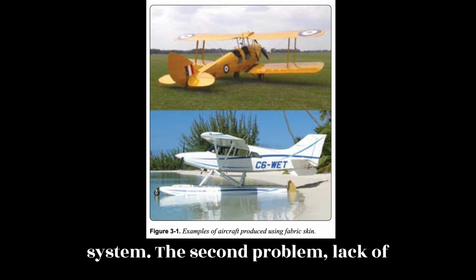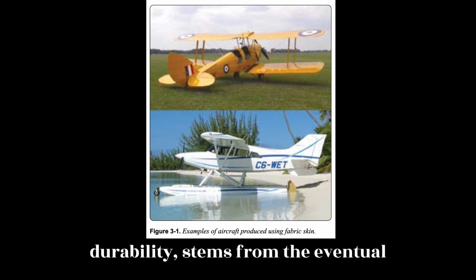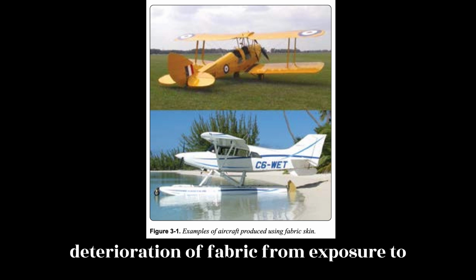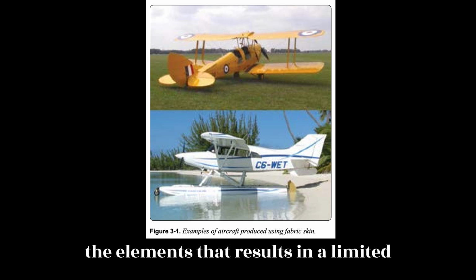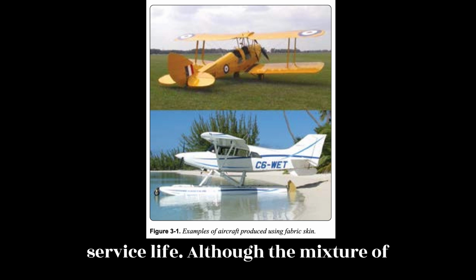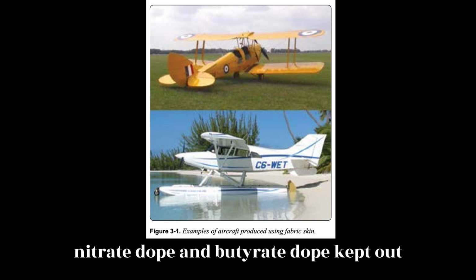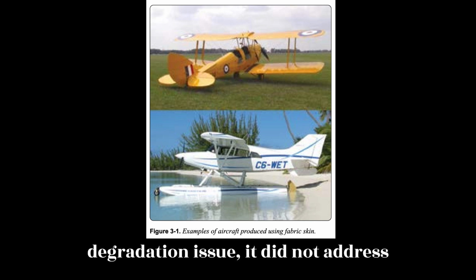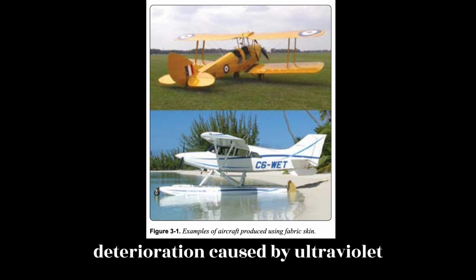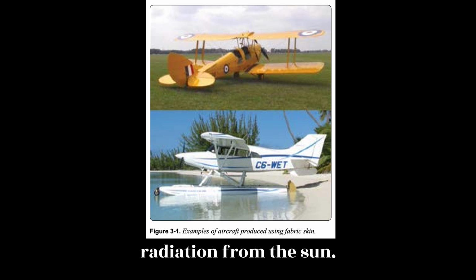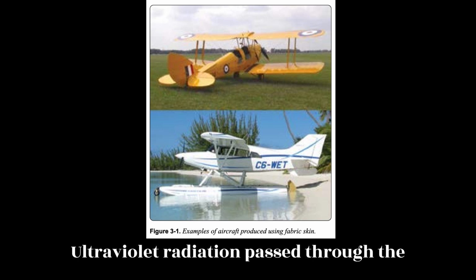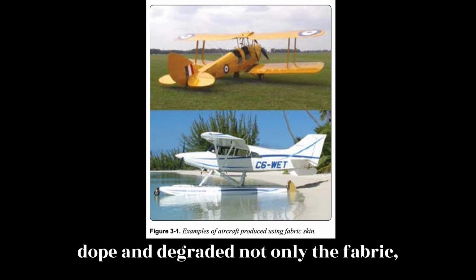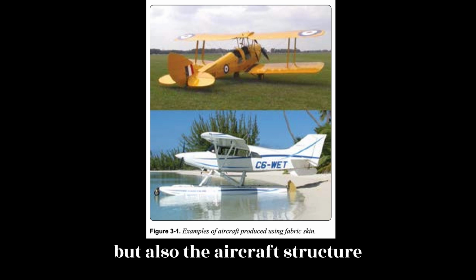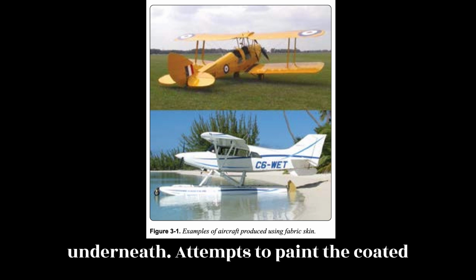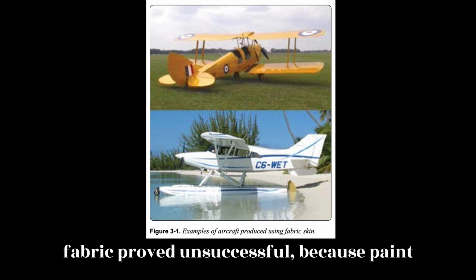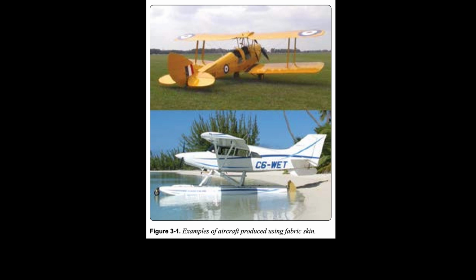The second problem, lack of durability, stems from the eventual deterioration of fabric from exposure to the elements that results in a limited service life. Although the mixture of nitrate dope and butyrate dope kept out dirt and water, solving some of the degradation issue, it did not address deterioration caused by ultraviolet (UV) radiation from the sun. Ultraviolet radiation passed through the dope and degraded not only the fabric, but also the aircraft structure underneath. Attempts to paint the coated fabric proved unsuccessful, because paint does not adhere well to nitrate dope.